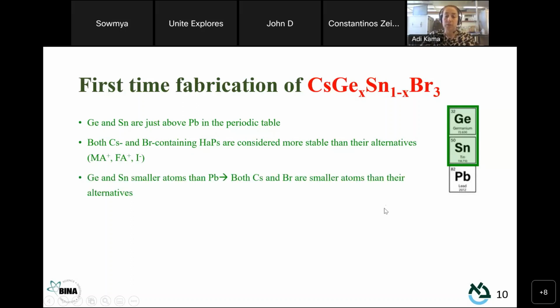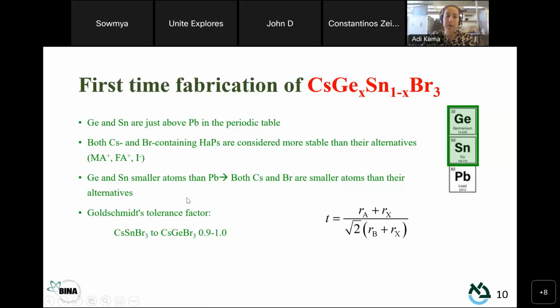When we choose elements to construct this structure, we need to think about the size. Both germanium and tin are smaller than lead and therefore require smaller atoms in the structure to make it stable. Stability is defined by the Goldschmidt tolerance factor, which is basically a relationship between the atomic radii of the A, B, and X elements. For cesium tin bromide, the tolerance factor is 0.9. For cesium germanium bromide, the tolerance factor is 1, and it's assumed to be more stable, moving closer to 1. Bandgap tuning is possible between 1.8 for the pure cesium tin bromide and 2.5 for the pure cesium germanium bromide.